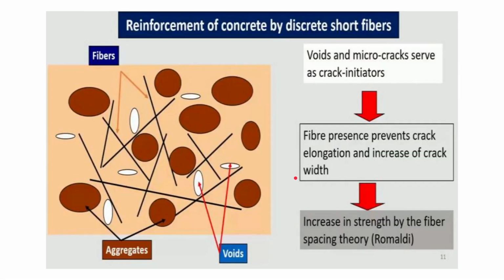Reinforcement of concrete by discrete short fibers. As you can see, these are the aggregates, these are the voids, and these black lines are the fibers. If you see this void, for example, it is surrounded by these fibers, which does not allow the void or the microcracks to serve as crack initiators. So these fibers prevent the crack elongation and increase of crack width. That is the use of these fibers, and that results in an increase in strength by the fiber spacing theory, which has also been investigated by Romualdi.